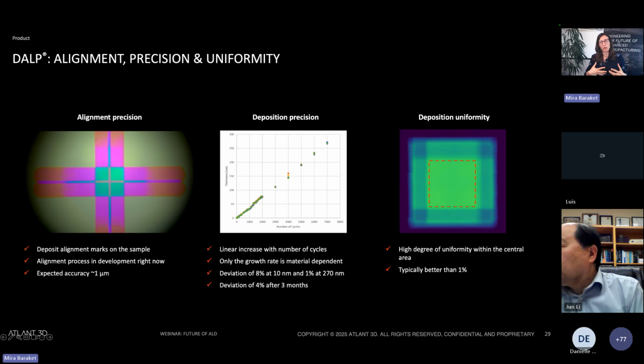Since we are creating some devices, this means that the deposition can sometimes be done in alignment with other pre-existing patterns. That's why it's very important to have an accurate alignment, and we are able to achieve an accuracy of 1 micrometer. In terms of precision and repeatability of our deposition process, we constantly have processes and continuous quality control, and we are able to get to a deviation of the process as low as 1%.